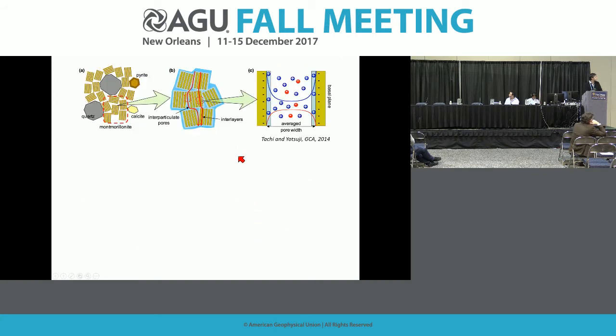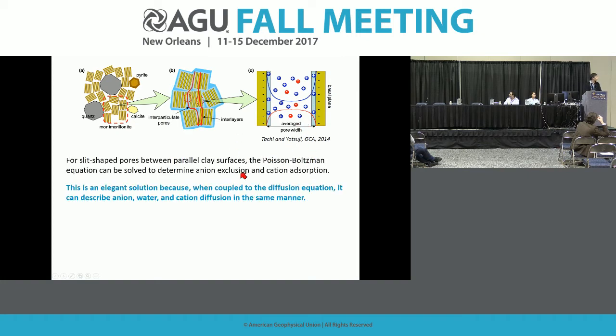If you want to explain this, we have to come back, in fact, to the description of what is going on at the clay pore size level. So if we want to do that very simply, we can do it like this. You homogenize the system and say, okay, the system can be modeled with only one pore size, and in this pore size, you apply both a diffusion law and the fact that you have a cation and anion distribution that follows the Poisson-Boltzmann equation. So if you do that, it's a very good solution because you can fit all of the data I've shown before, and you can describe anion, water, and cation diffusion in the same manner.